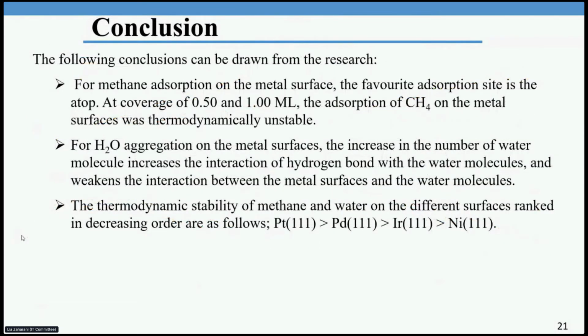Conclusion. The following conclusions can be drawn from the research. For methane adsorption on the metal surface, the favorite adsorption site is the atop site. At coverage of 0.5 and 1.0 monolayer, the adsorption of methane on the metal surface was thermodynamically unstable. From water aggregation on the metal surface, the increase in the number of water molecules increases the hydrogen bond interaction between the water molecules and weakens the interaction between the metal surface and the water molecule. The thermodynamic stability of methane and water on the different surfaces is ranked in decreasing order: platinum 111, palladium, iridium, nickel.